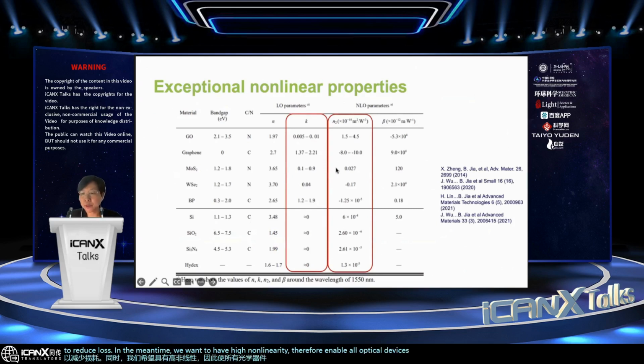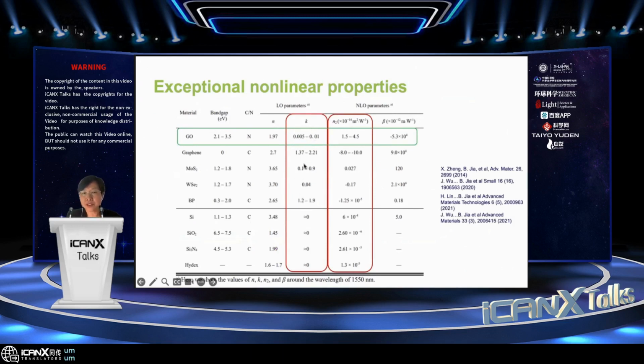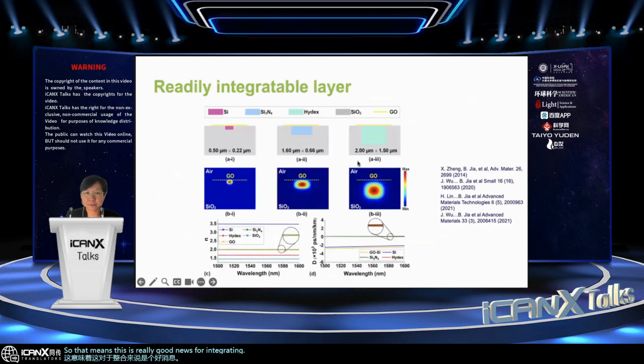We found that compared to other materials, graphene oxide really gave you a good property. So in terms of linear absorption, it's really low, which is orders of magnitude lower than other 2D materials. And in terms of N2, it is actually orders of magnitude higher than other atomically thin materials. So that means this is really good news for integrated devices.